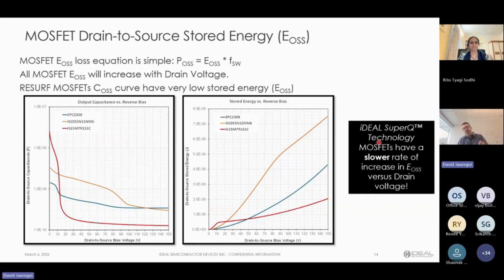But so there's that switch loss element. Then there's, okay, what about the amount of energy you store in that capacitance itself? There's that CV curve here. And when it comes to that parameter, what matters there is the stored energy, or what we call EOSS, which is really just the integration of the CV curve, really the integration of the charge over voltage, which gives you the energy. And what I'm comparing here are basically three MOSFETs of the same RDS(on), right? I don't want to just show you curves that are irrelevant. I want to normalize it so that for the same RDS(on), you can do a direct comparison of the capacitance curve. And sure enough, here we are with very high capacitance, and we drop quite sharply, and then we end up with very low capacitance.